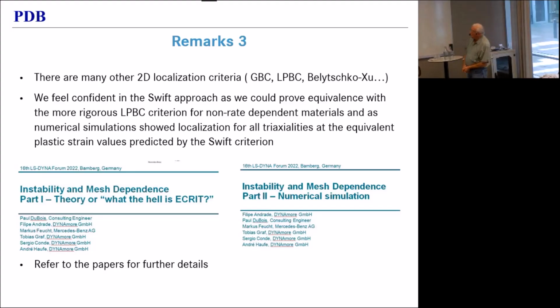Well, number one, it's very simple. Number two, as long as the material is not rate dependent, and these things become very, very complicated once you consider rate dependency. But as long as your material is not rate dependent, we could actually prove that it gives the same results as the limit point bifurcation criterion, which is much more complex and has a much more solid mathematical foundation. But the main reason is that we tested it.